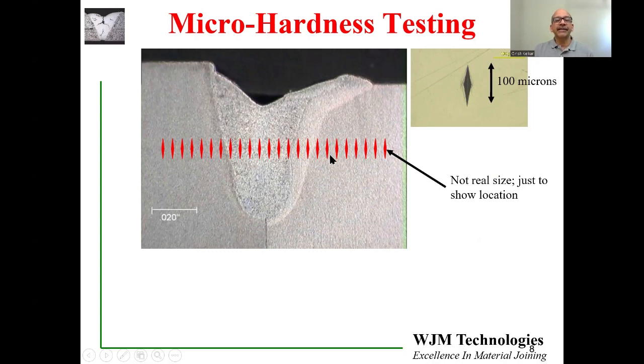What we are interested in finding out is if certain zones in the weld have become very soft or very hard compared to the base metal. And it can be both. The fusion zone can be harder or softer, or sometimes even the heat affected zone can become harder or softer compared to the base metal. How does it affect welding? A zone, in any zone, which is much harder than the other, is more susceptible to crack growth. So let's say in this case, this is the fusion zone, and let's say the fusion zone ends up being harder than normal or compared to the base metal.